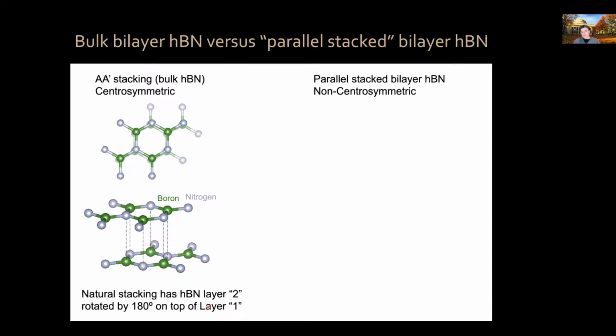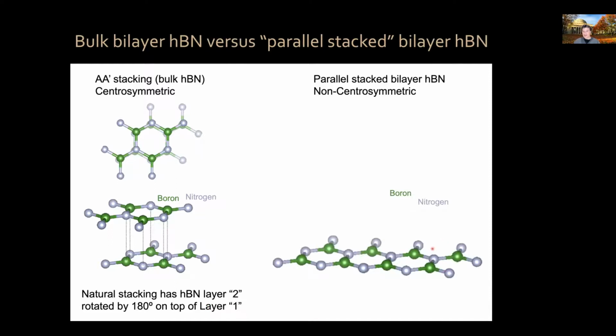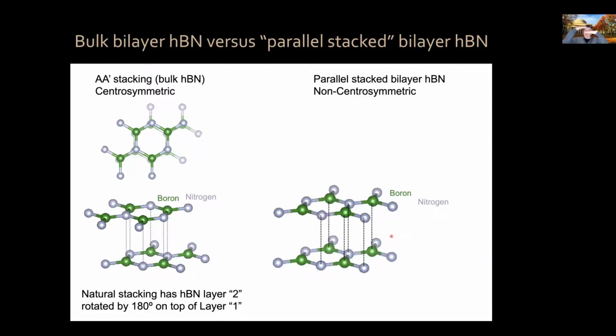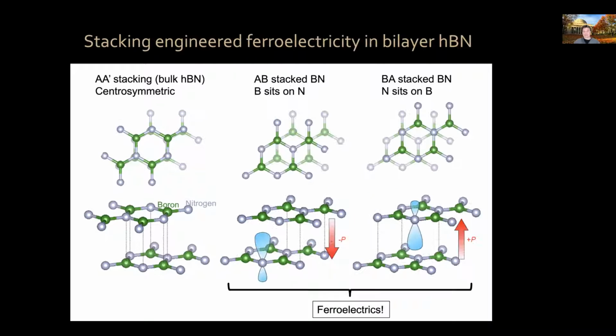Now, if we take a single layer of boron nitride, let me point to the locations of the atoms, boron and nitrogen. Now we break it and we stack it parallel to itself. So with 0-degree angle between layer 2 and layer 1, you can see that nitrogen atoms are on top of nitrogen atoms, boron on top of boron. Now, this is a non-centrosymmetric arrangement. It's also very uncomfortable for the system, so the system decides to shift towards AB stacking or BA stacking. And it turns out that these 2 configurations, AB and BA stacking, have electric dipole moments which are opposite of each other. So if we can switch somehow between these 2 configurations, we have a switchable ferroelectric.